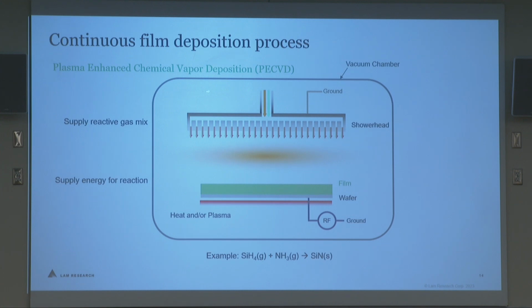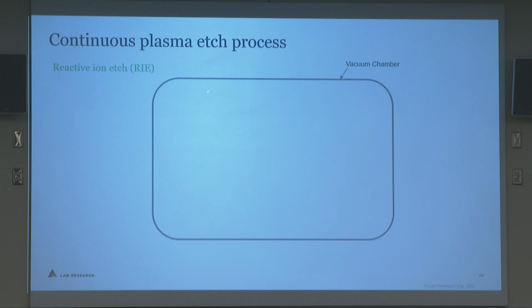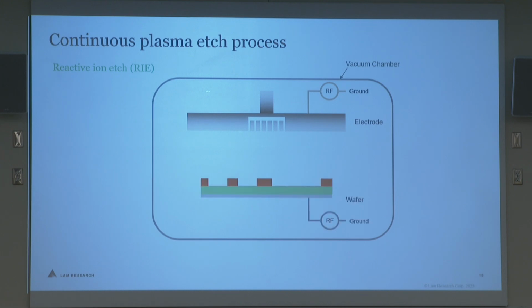So the reverse process, if you want to look at an etch process, is reactive ion etch, which is kind of the traditional product for Lam initially, and also a standard for the industry. Again, you've got a vacuum chamber. Same sort of thing: you have a top electrode for the plasma, and the white bit or the holes from the shower head is where the gases are going to come in. You have your wafer, but this time you've already got a film and a pattern on top of it. And the film is what we want to remove. The green layer is the film, and the brown one is what we would call an etch mask. We don't want to remove the film that's under that mask.